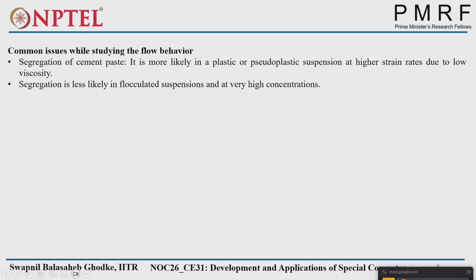So what are the common issues? Segregation of cement paste. It is more likely in plastic or pseudoplastic suspensions at higher strain rates. If you have a cementitious mix, you provide a certain shear rate, and then you increase the shear rate for another material. Obviously, both give different results because shear rate or strain rate is very important. If you are mixing at a higher rate, you will get different values, and there is a possibility that with the higher strain rate, the larger particles will get separated from the matrix. That is called segregation of cement paste.